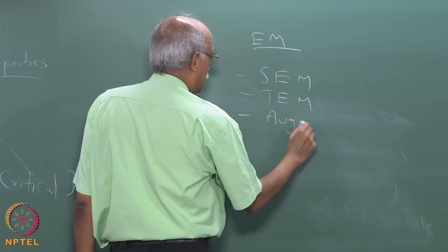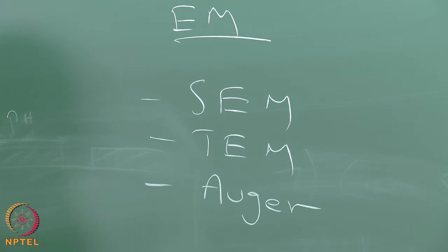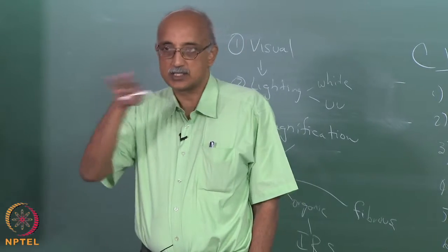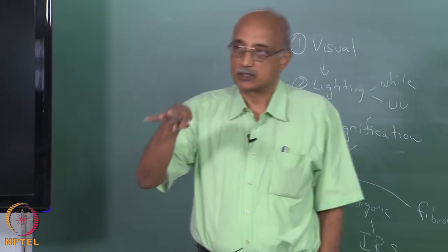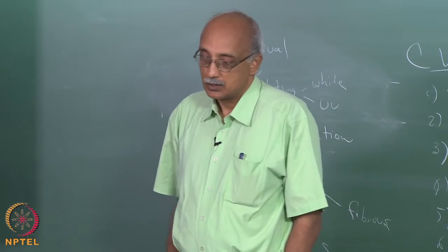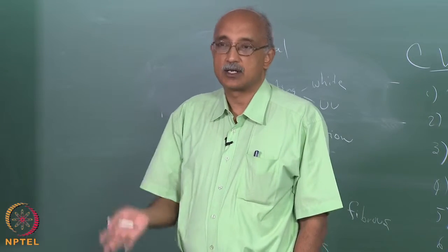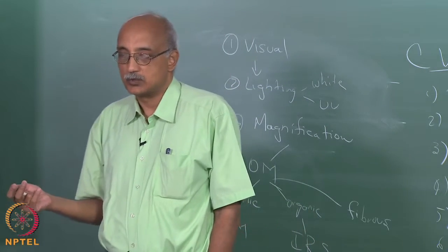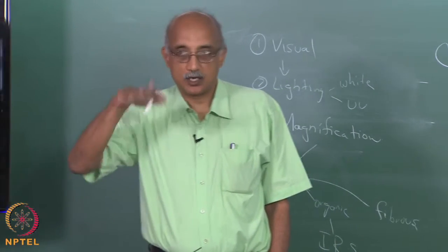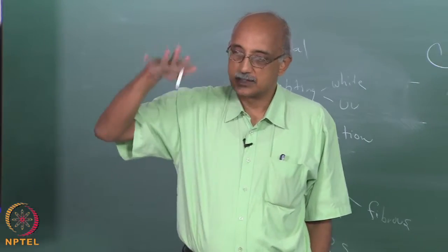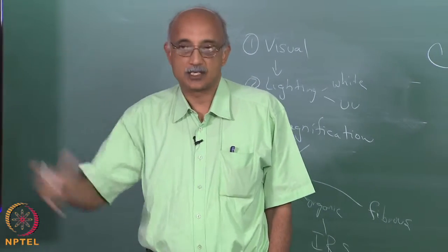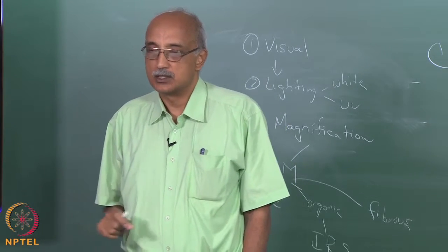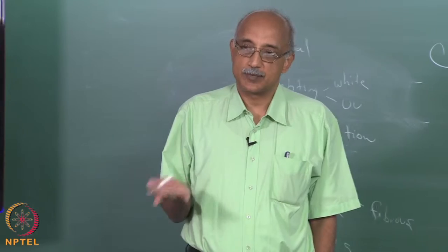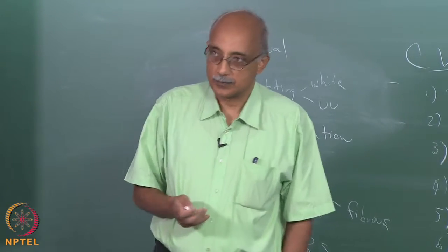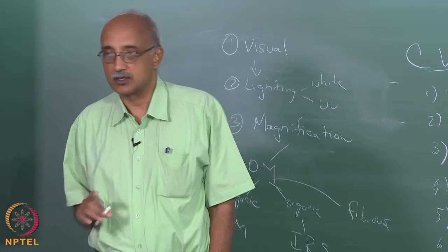There's also a technique called Auger electron spectroscopy. Auger electrons are the electrons that are knocked off from the first layer when you irradiate a sample with an electron beam. Auger analysis, therefore, can be used for sectional analysis of a CVD film. So you would essentially continuously knock off electrons from various depths of the CVD film and do the SEM analysis and the EDS analysis and so on. So it gives you depth profiling capability. So that's a big advantage of Auger spectroscopy. It's spelled A-U-G-E-R, not OJ.